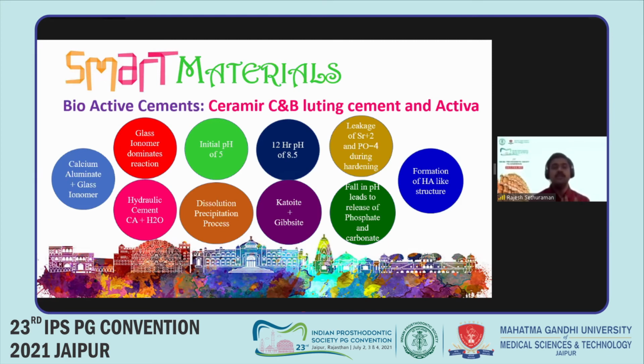In addition to this, they also are smart, because with the loss of pH, extreme reduction in pH, they release phosphate and carbonate ions to form a hydroxyapatite-like crystal. So therefore, choose these bioactive cements in order to lute your restorations.